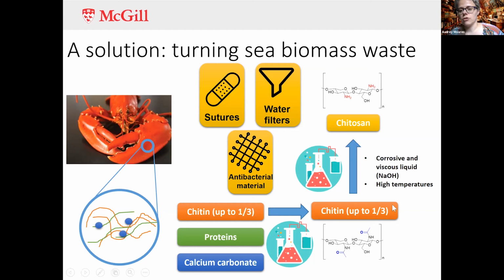This process necessitates working with concentrated solutions of sodium hydroxide, which means that you have a very viscous, corrosive liquid that you need to heat. You need to add this liquid in large excess to the chitin that you're treating.